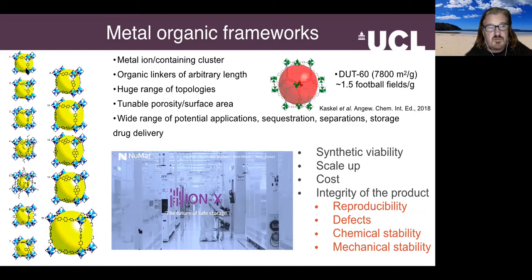It's an example of something called a reticular material. The nice thing about this is you can preserve the topology of the underlying material, but you can vary the functional groups in between. So that varies the chemistry, and because you can vary the chain length, you can also vary the porosity. And the huge porosity of these materials recommends them to a large variety of different potential applications, including sequestration, separations, storage, even drug delivery. Some of the pore apertures can be in excess of 100 angstroms, so they're really very large indeed.